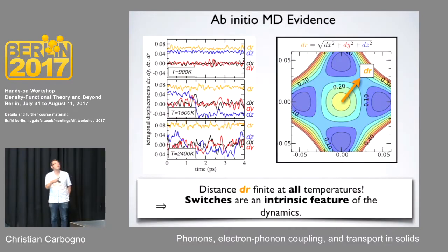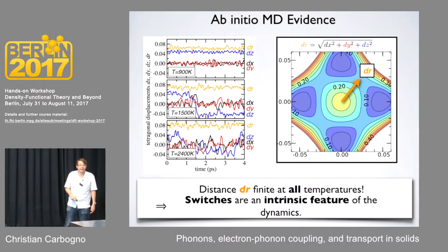And this brings you again back to the plot that I've shown you before, where I said that at high temperatures you start to have these switches between different minima, and this is related to the fact that the harmonic approximation breaks down. With that you get strong anharmonic effects whenever you switch from one minimum to the other in this material. And if you start understanding that, you can start tuning it and looking at how much, for instance, a defect would change your thermal conductivity.